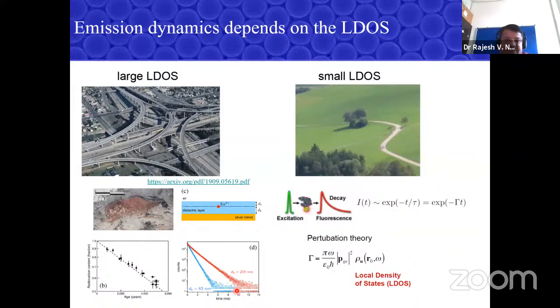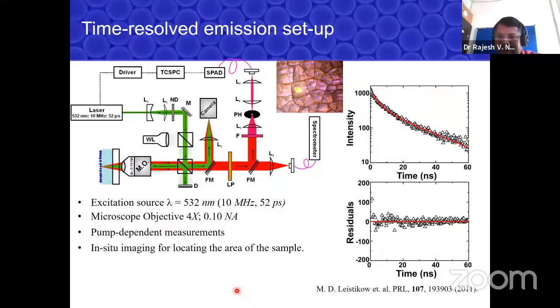So we did another experiment. We had to build up facilities again, because a commercial system doesn't help you here, since the signal has to be collected from regions of tens to 150 microns. So we built a time-correlated single photon counting decay rate measurement system. Again, we have a picosecond green laser, which excites the dyes and we collect the emission. Again, we send it to a camera, because we want to know whether we are measuring from the right region. And this is a typical decay curve we get in the lab.